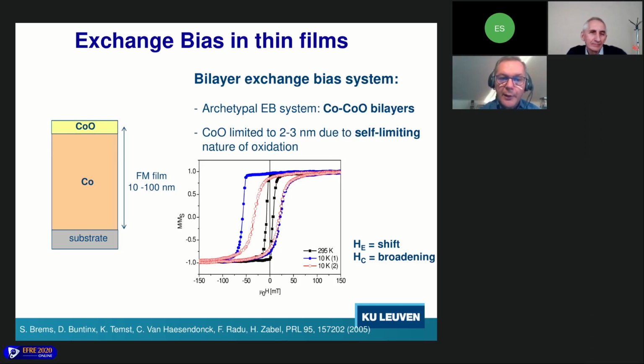You also can remark that the shape of the loop is not symmetric. It's very straight and vertical here, but it is much more rounded on this side. And this is a peculiar phenomenon in exchange bias, which indicates that the magnetic reversal mechanism is different on the two sides of the loop. And then if you measure the hysteresis loop again, you also see that the shape is changing once more. This is the so-called training effect. So this has been studied in a lot of detail, but as I said, the big limitation is that you cannot play with the thickness of this cobalt oxide layer.